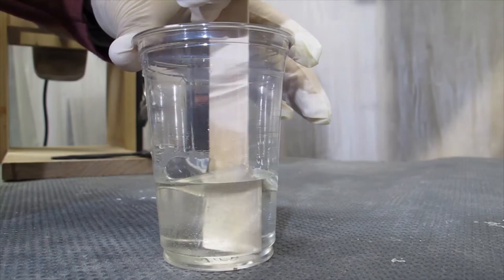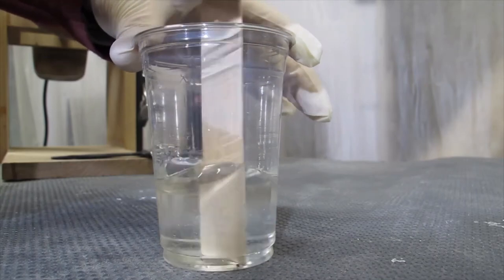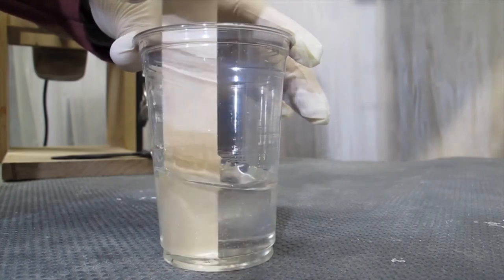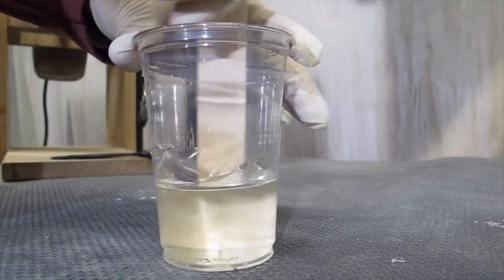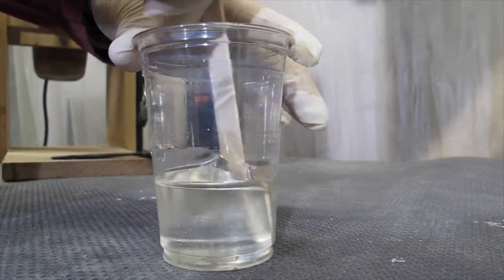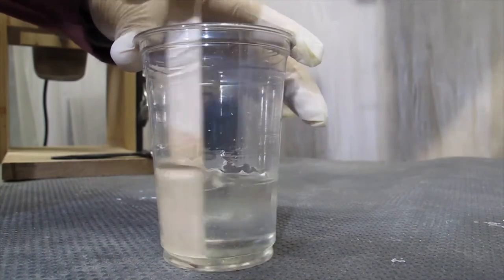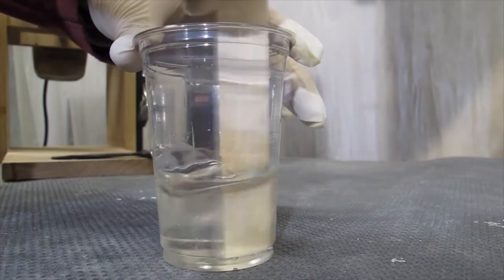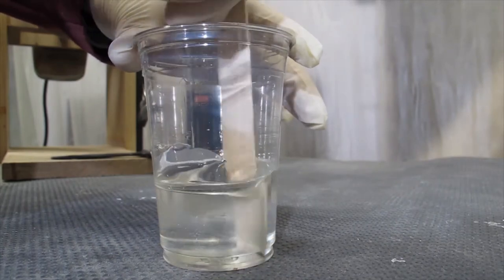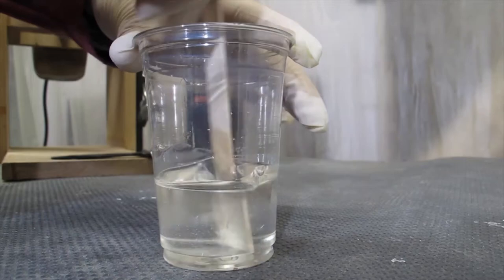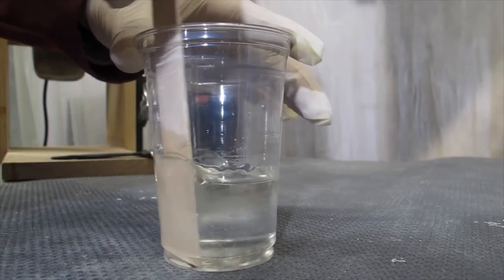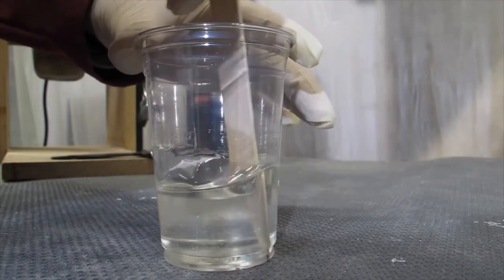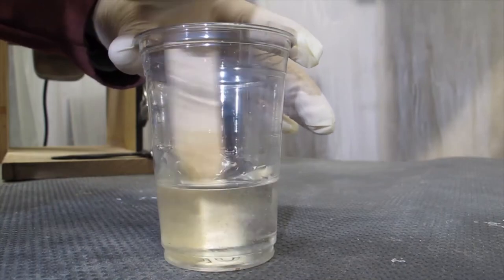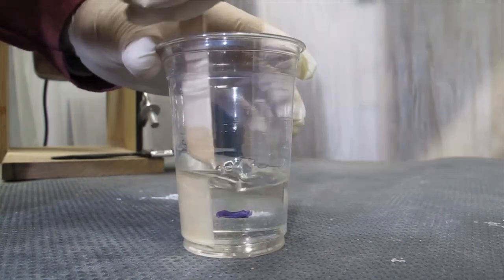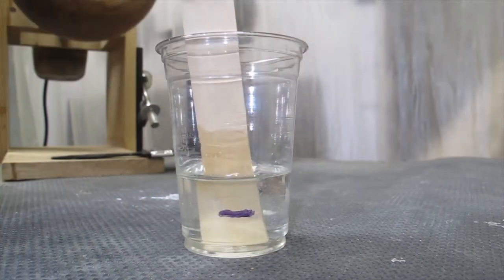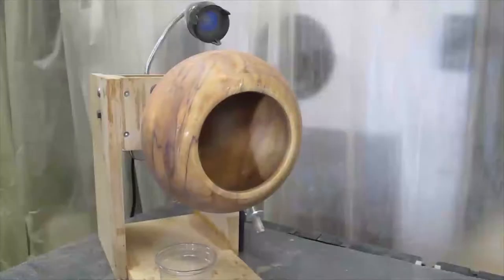By putting the hardener in first, and then pouring the epoxy resin through the hardener, it will always make contact with all of the epoxy resin, and the resin can't stick to the sides of the glass. That is where you'll get issues with resin not curing properly. If you don't scrape it off the edges thoroughly enough, you'll have soft spots in your resin, or resin that hasn't cured. There you go, it's finished mixing. Now I can start applying it.